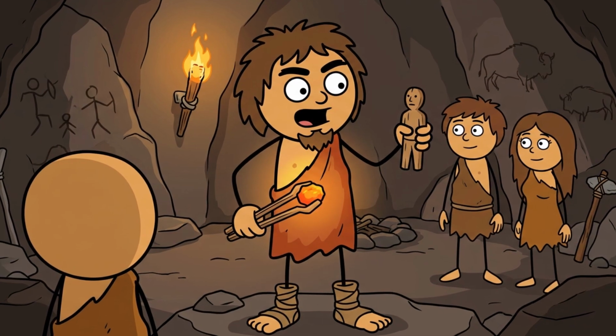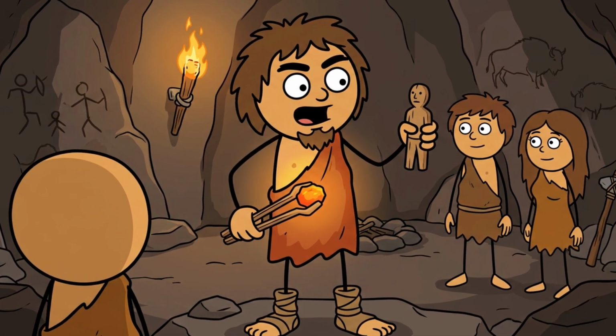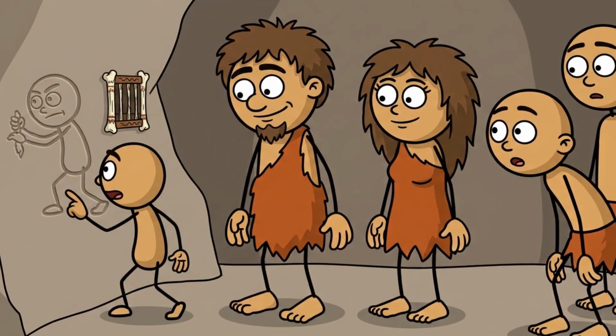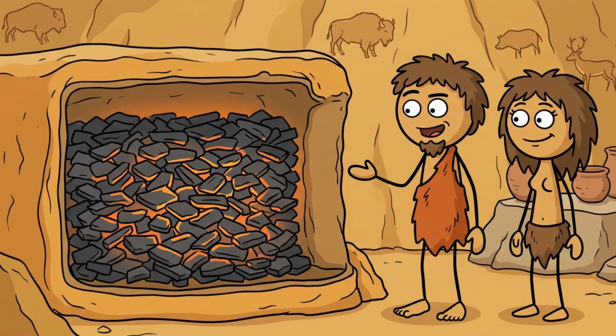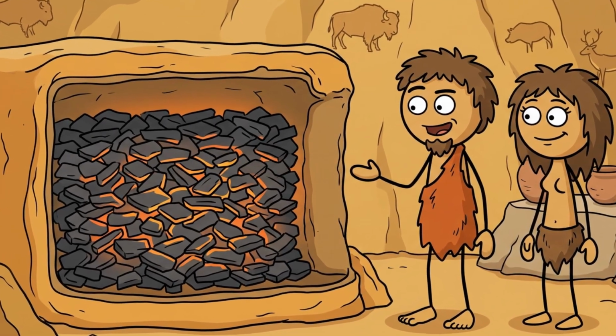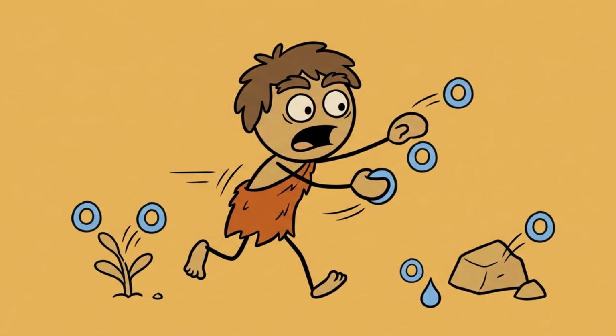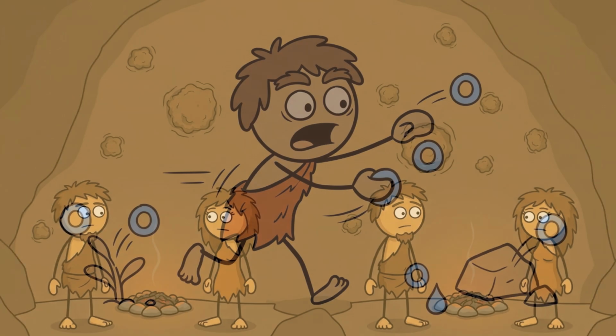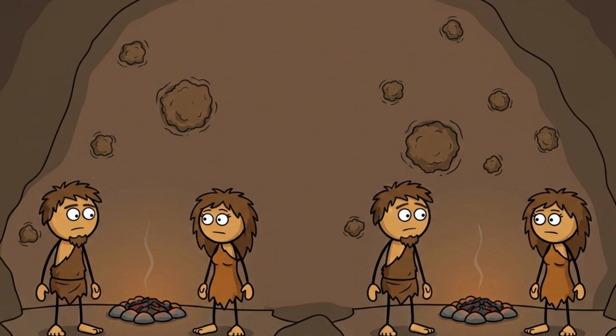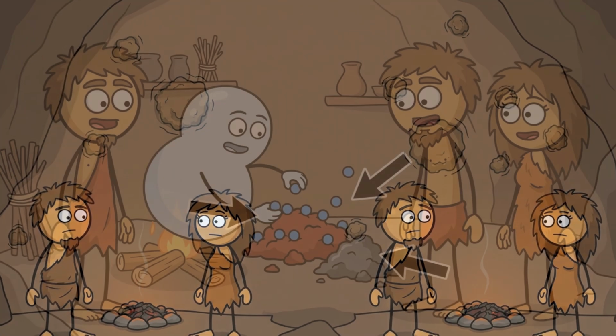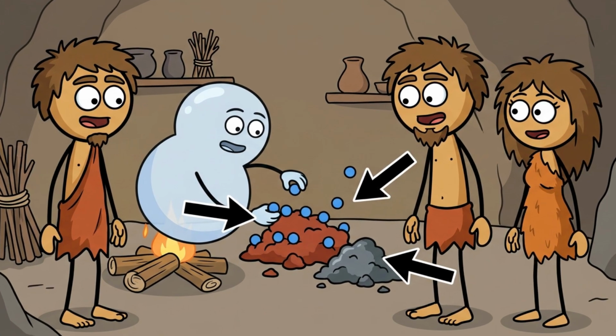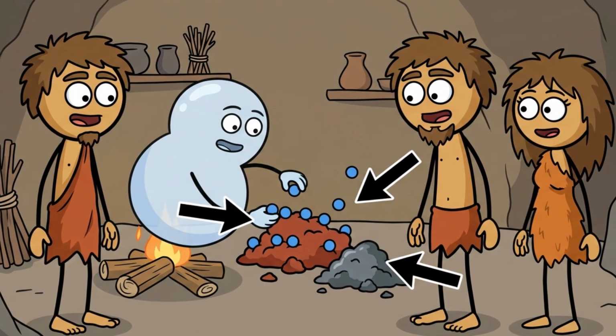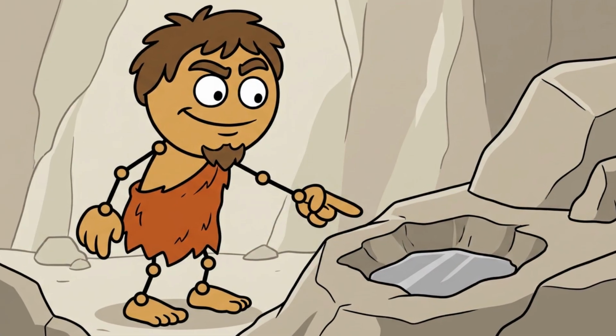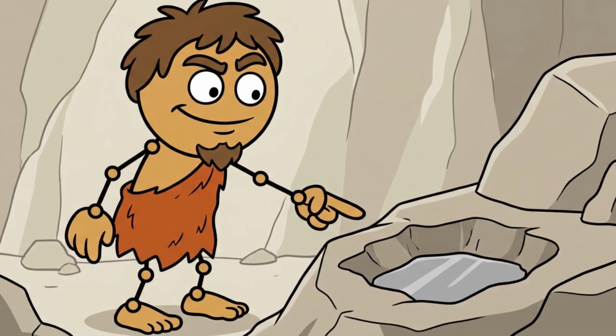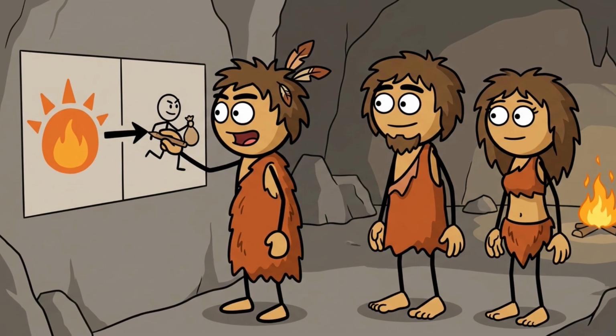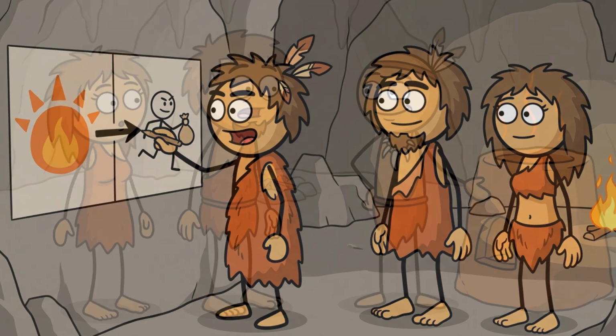The metal is right there, and it is held shut. To open it, you need 2 things at once: enough heat and a chemical thief. The thief is the part people forget. Charcoal in a sealed hot space does not simply produce heat. Starved of air, it produces carbon monoxide, a gas that is desperate for oxygen and will pull it off almost anything it touches. That gas walks up to an iron oxide, takes the oxygen away, and leaves metal behind. So a furnace is not a hot box. It is a chemical argument, and heat is only one side of it.